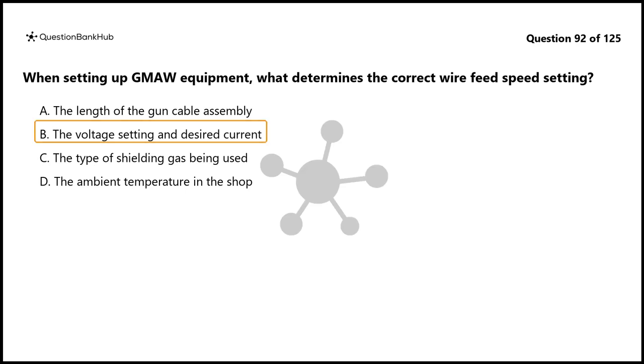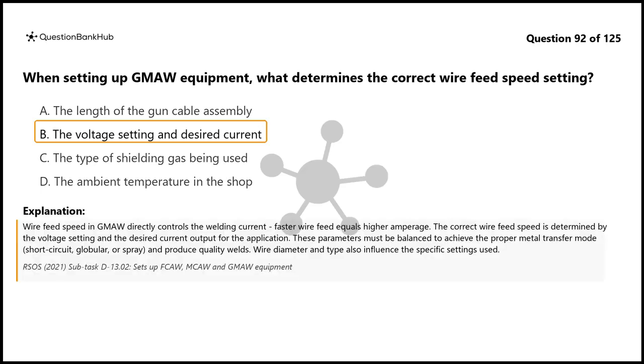The correct answer is B. The voltage setting and desired current. Wire feed speed in GMAW directly controls the welding current. Faster wire feed equals higher amperage. The correct wire feed speed is determined by the voltage setting and the desired current output for the application. These parameters must be balanced to achieve the proper metal transfer mode, short circuit, globular, or spray, and produce quality welds. Wire diameter and type also influence the specific settings used.